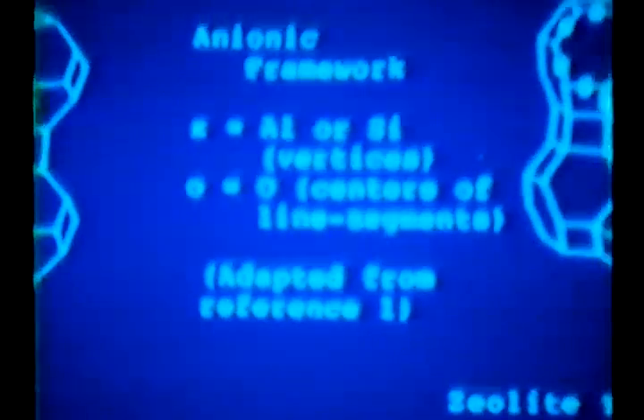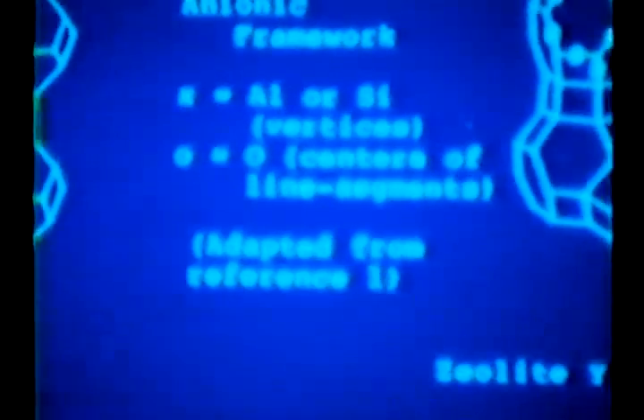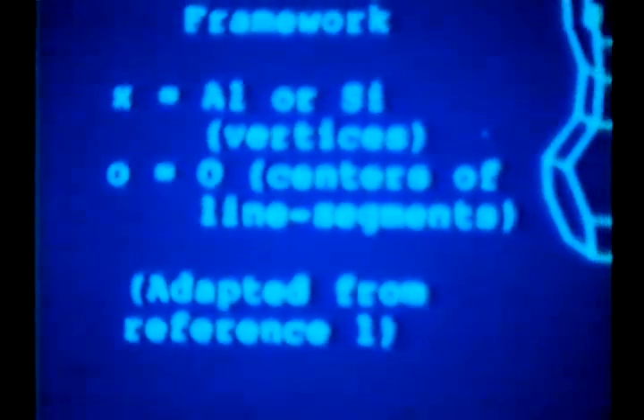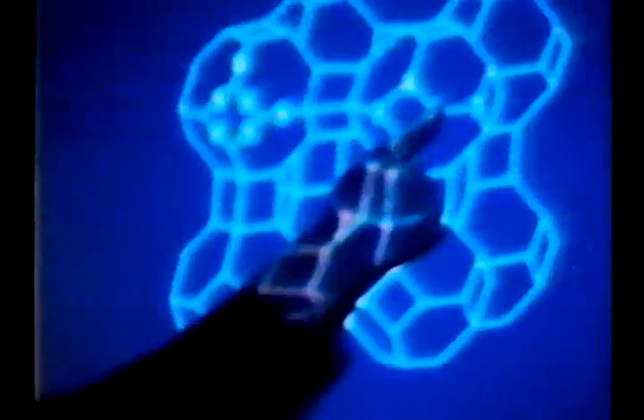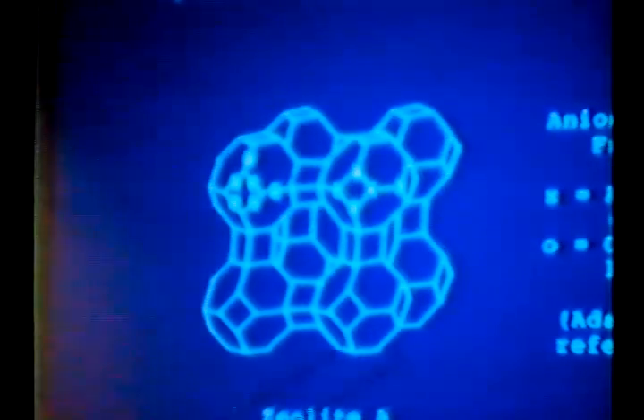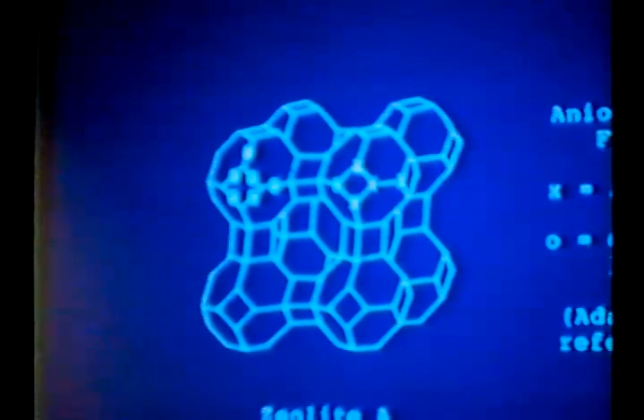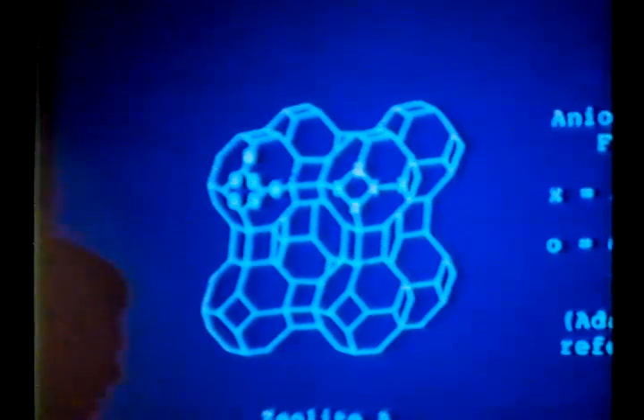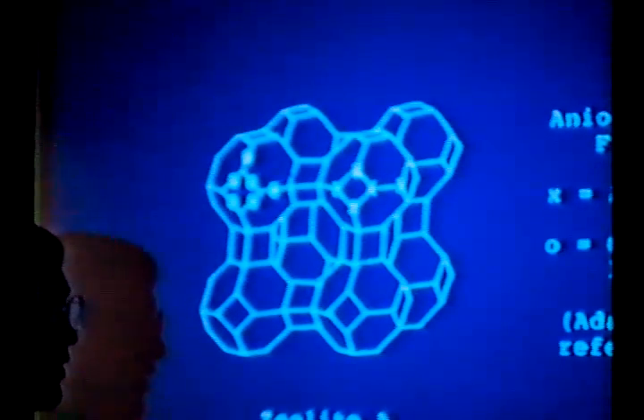So, these are aluminum silicates. They have aluminum, silicon, and oxygen in them. And this type of bond might be an aluminum, oxygen, silicon, oxygen, aluminum bond. The aluminums and silicons are in tetrahedral sites, and they are bridged by oxygen. So if we go around this six-membered ring, we have an aluminum or silicon, an oxygen, aluminum or silicon, oxygen, silicon. So this is an anionic framework, and cations can be exchanged in and out of these materials. It's one of the nice properties that we can make cation exchange zeolites. A typical formula might be this. It's a very big molecule, so water molecules as well are trapped inside here.